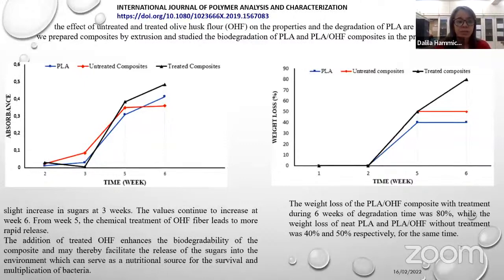As you can see on this screen, the left shows the sugar-related evolution from PLA and composite. Here we observed a slight increase in sugars at 3 weeks. The values continue to increase at week 6. From week 5, the chemical treatment of fiber leads to more rapid release. The initial degradation step of PLA consists of breaking down polymer chains into monomers, where the ester bonds are cleaved by hydrolysis. This can be used by the microorganisms, which leads to the production of carbon dioxide and biomass.